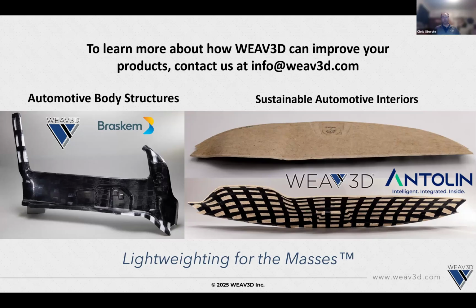It depends a lot on the material. In the case of the beltline stiffener, this part here on the left, we used an unreinforced polypropylene for the base bulk material. Because of that, and because of how much shrinkage polypropylene has, this part cannot be produced with lattice on only one side. It actually has to have lattice on both sides to get the symmetrical behavior.